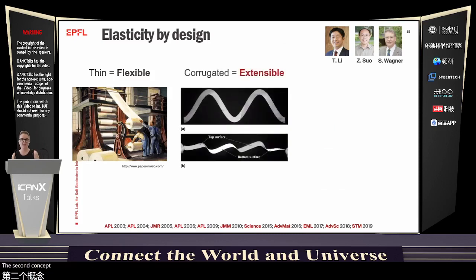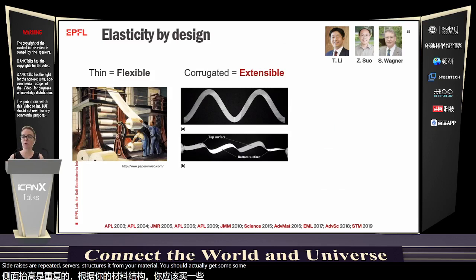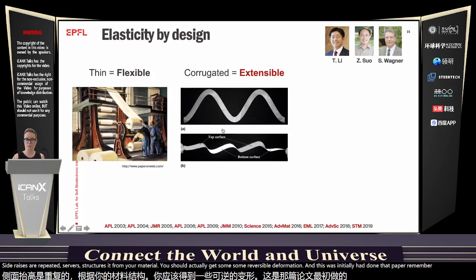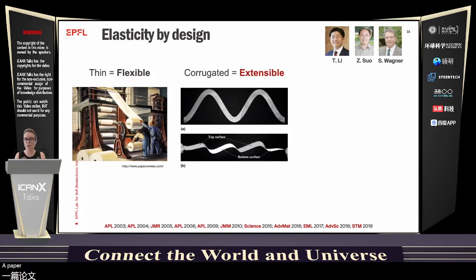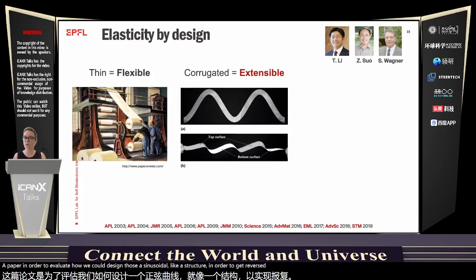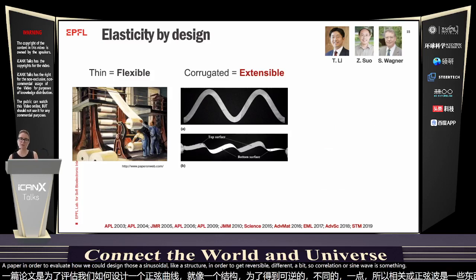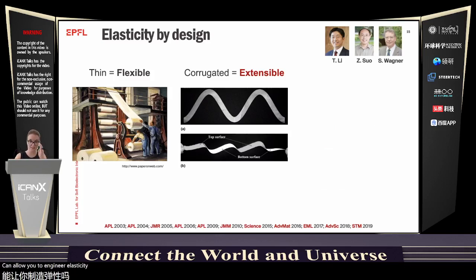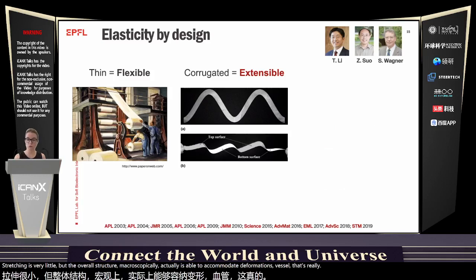The second concept is corrugation: if you pattern sideways or repeated structures from your material, you should get some reversible deformation. We initially did that with paper. I remember we literally used a piece of paper to evaluate how we could design those sinusoidal-like structures in order to get reversible deformability. So corrugation or a sine wave is something that can allow you to engineer elasticity. When you do such a design, the actual material itself stretches very little, but the overall structure macroscopically is able to accommodate deformation. That's really the trick in this design.